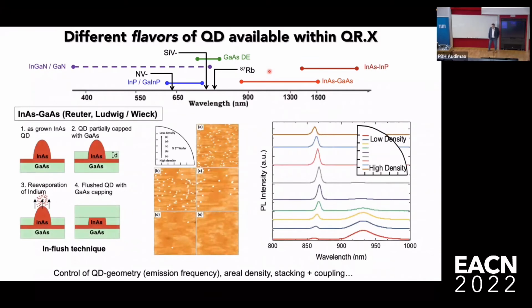To show you just two or three examples, the growth partners sent me a lot of material, but I only want to show you a couple of examples. This is the most commonly studied type of quantum dot, indium arsenide in gallium arsenide, emitting at around 950 nanometers. These days, you can control the height of the quantum dot with sub-nanometer precision to really control the frequency they emit. This is going to turn out for molecules later on to be very, very important.